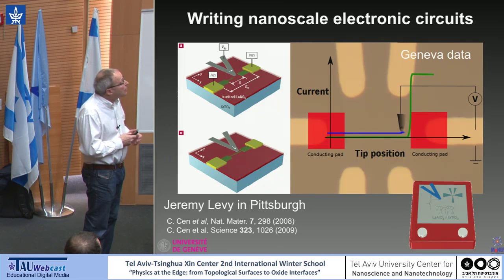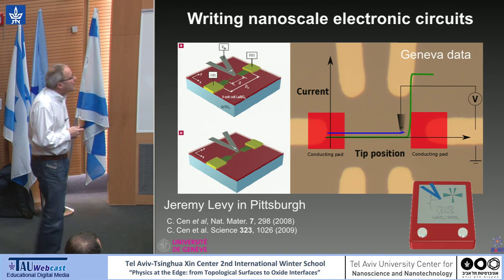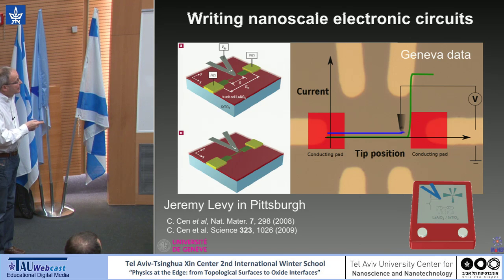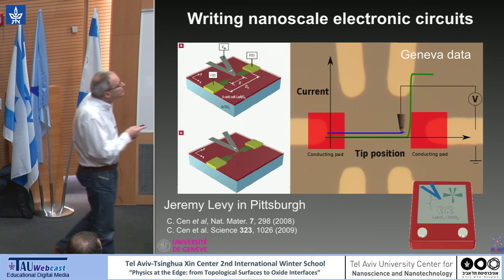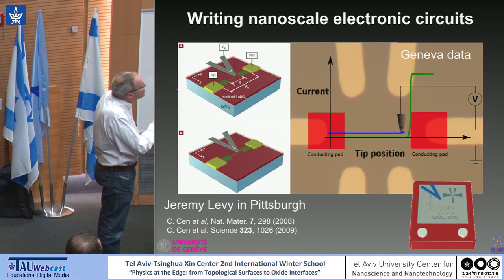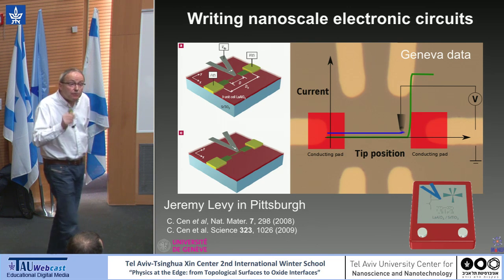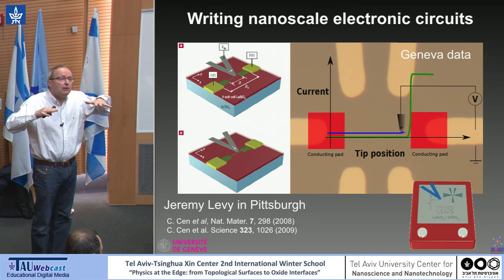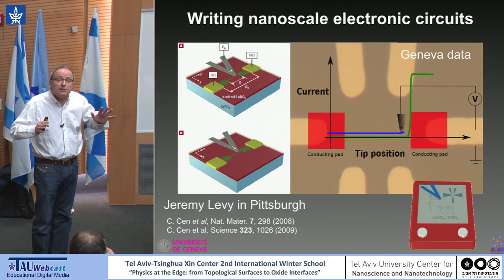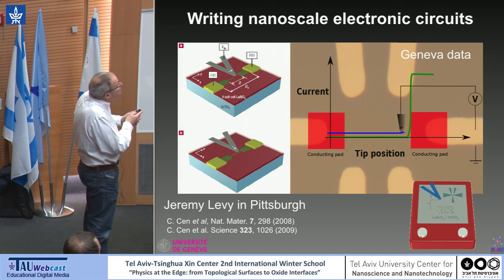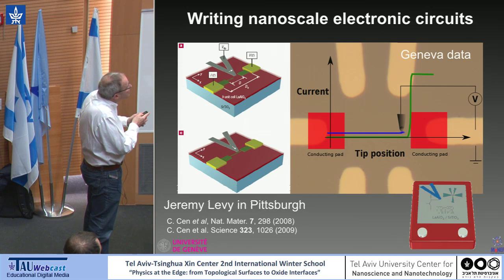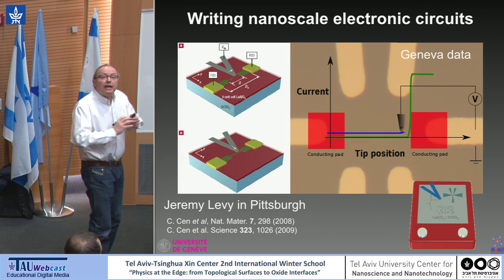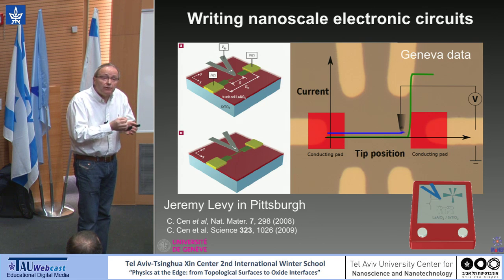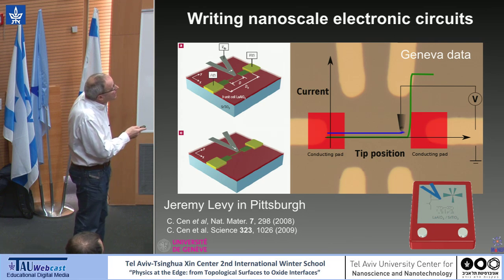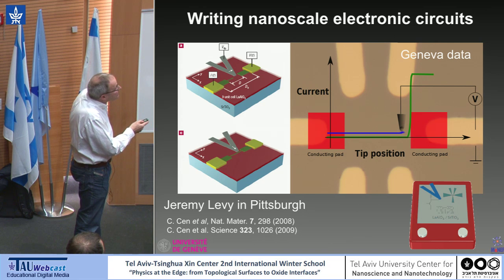There is great work on nanostructures following an idea of Jeremy Levy, who is really way ahead with this technique. And the idea is quite fascinating. What you can do is start with a layer thickness of LaAlO3 of 3 unit cells. If you remember, 3 unit cells is just below the threshold. So the system is insulating. But if you come with an atomic force microscope with a metallic tip, and you have contact, and you apply a bias, you can induce the conducting layer just under the tip. And this is stable. And doing this, you can write nanostructures.